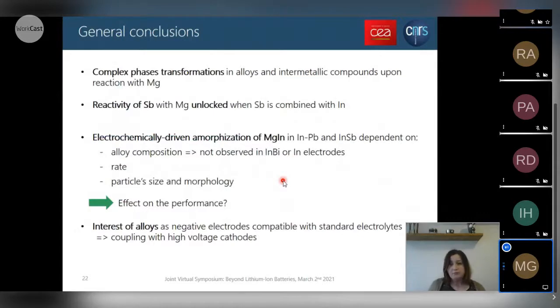So we arrive finally to the conclusion. So I hope that I showed you the complex phase transformations that can occur in alloys for magnesium batteries. We have designed 2 new alloys, and in the InSb alloy, we have shown that we were able to really unlock the reversibility of antimony when it's combined with indium.